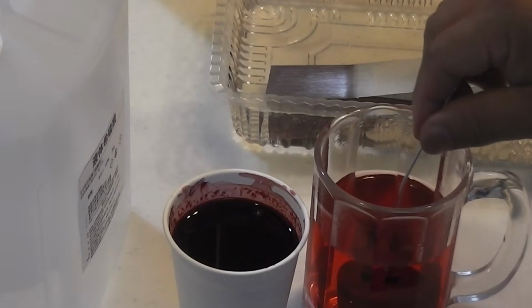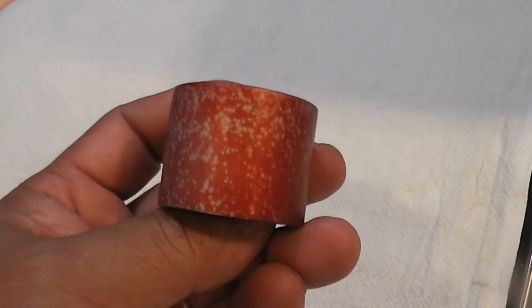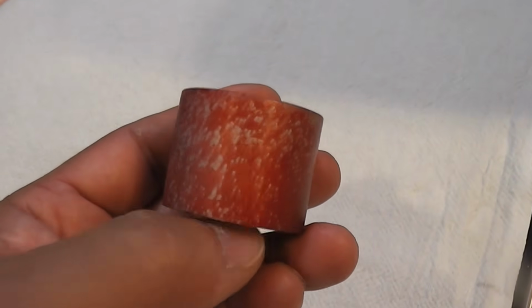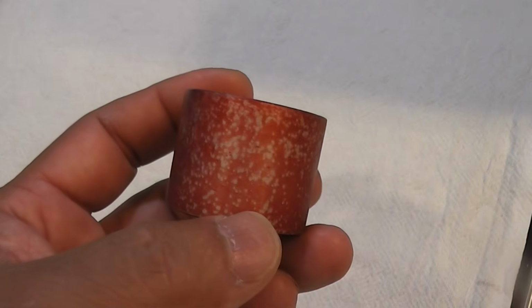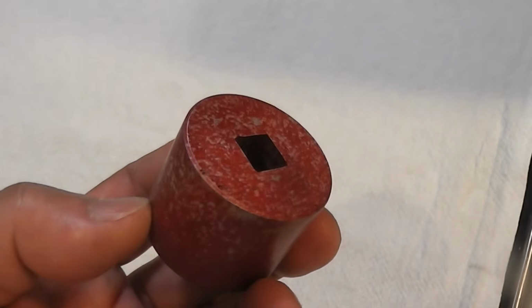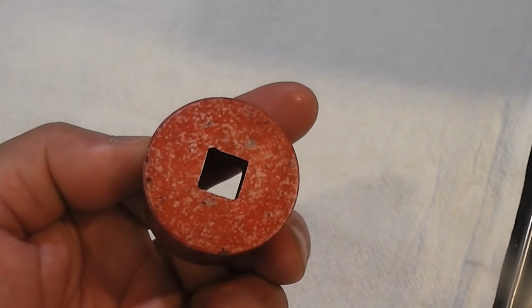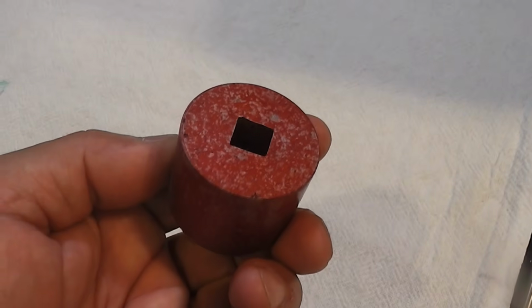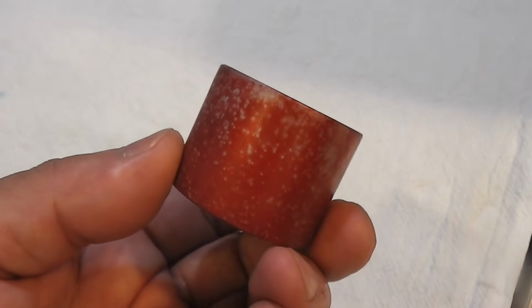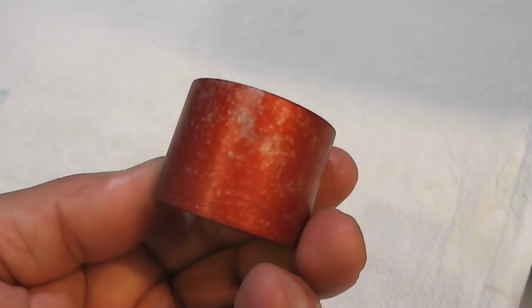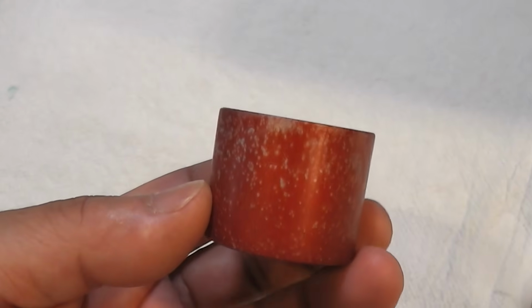Now, let's compare the two parts. The first aluminium socket developed numerous white spots across its surface. These spots appeared because oxygen bubbles remained attached during anodizing. Each bubble blocked the electrolyte, preventing a uniform oxide layer from growing underneath. Without a proper oxide layer, those areas couldn't absorb the dye, leaving visible white defects.